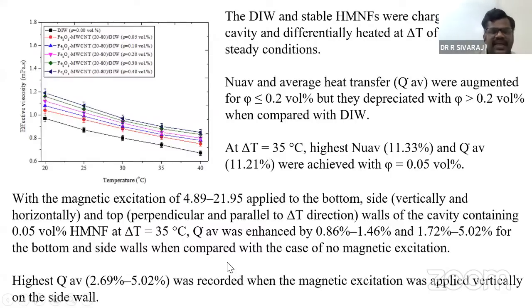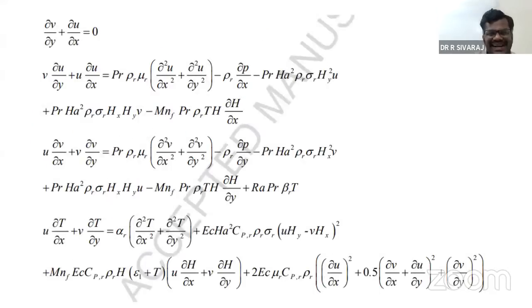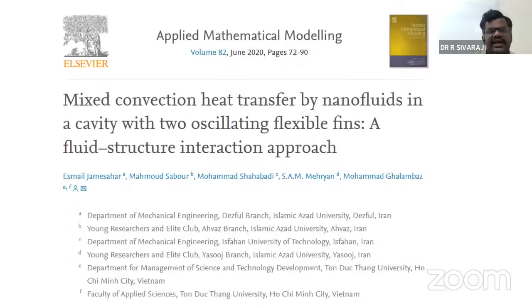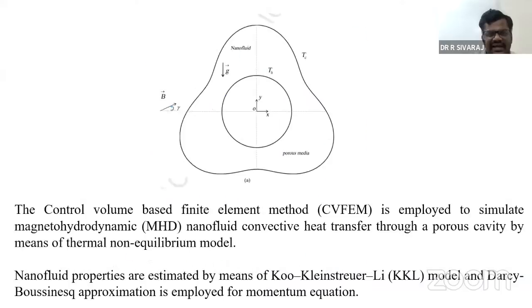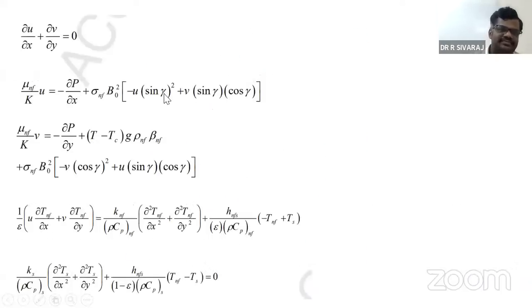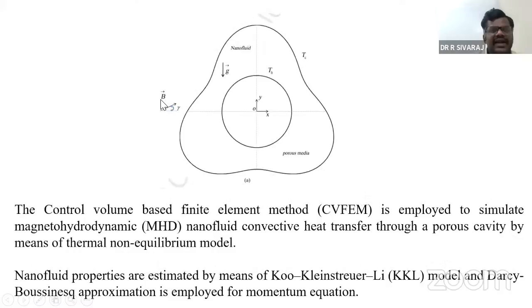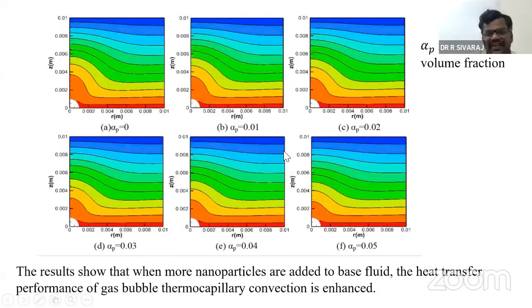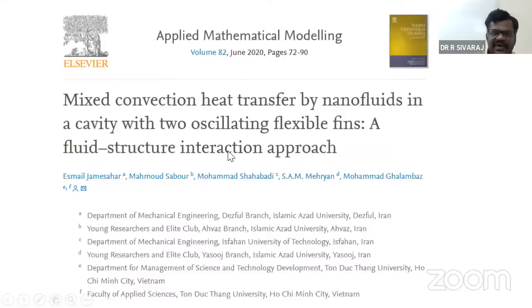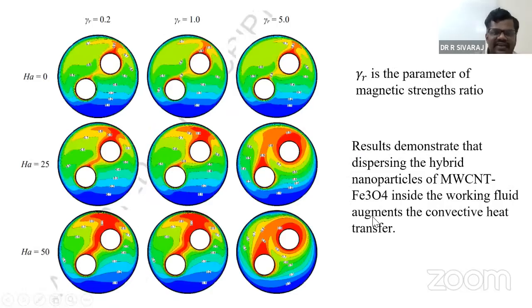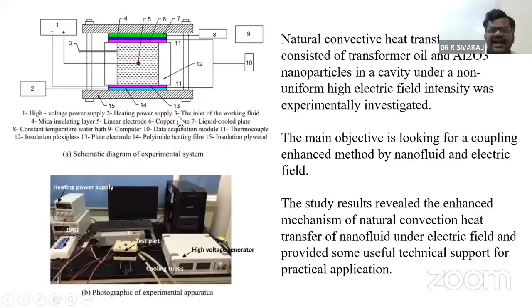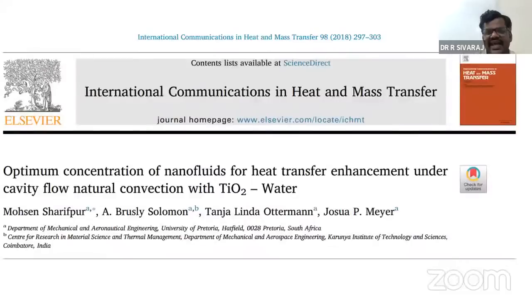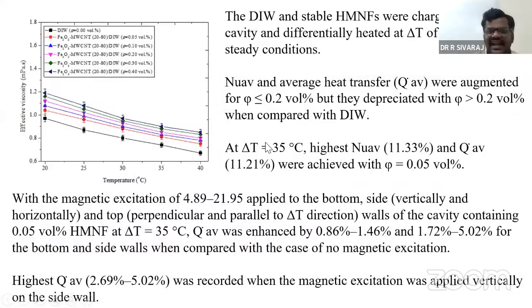And the same thing here: suppose you want to change the inclination angle of the magnetic field. In the theoretical study, the magnetic field inclination angle can be changed through this value gamma. And when we change the magnetic values, for example for different volume fractions, how the heat transfer rate changes, we have studied theoretically here, and there experimentally. So what are the results? Qualitatively, we can definitely say that they match exactly. And physically, in value, most of the time we have almost the same results.